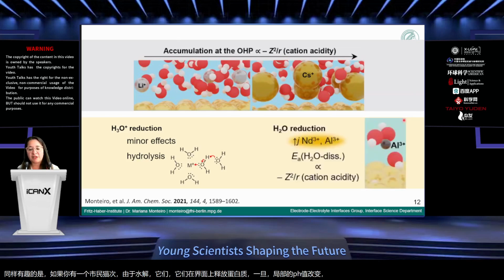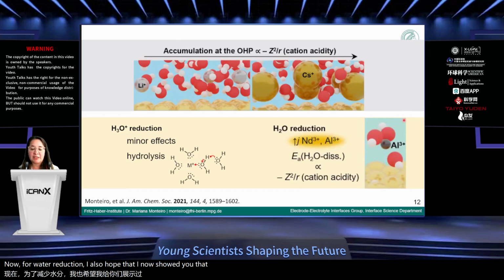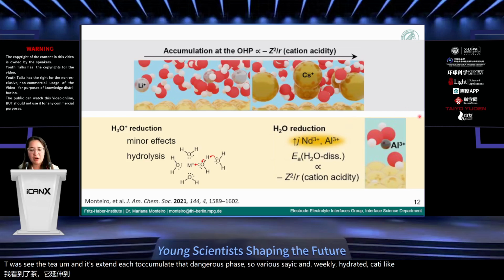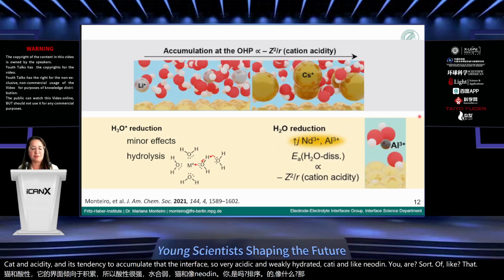Now, for water reduction, I also hope that I showed you that you have to have a compromise between cation acidity and its tendency to accumulate at the interface. So very acidic and weakly hydrated cations, like neodymium, are the best compromise between the two things.